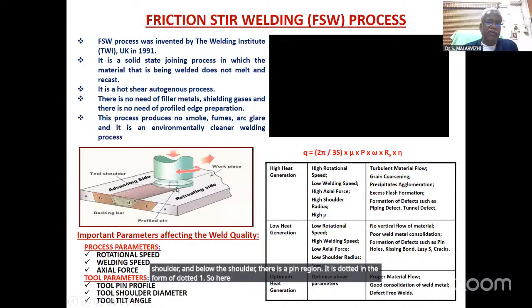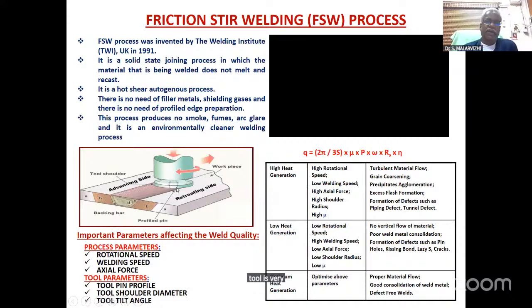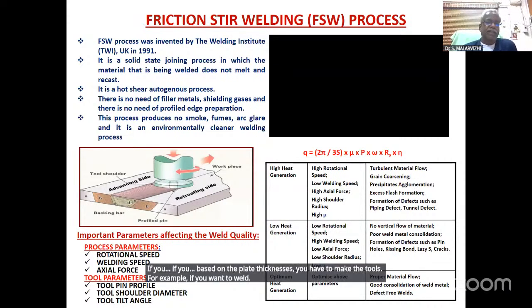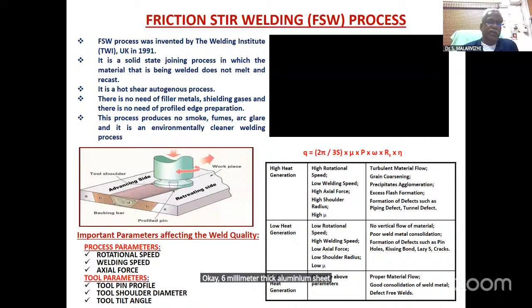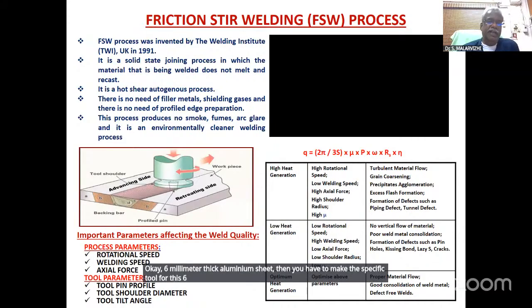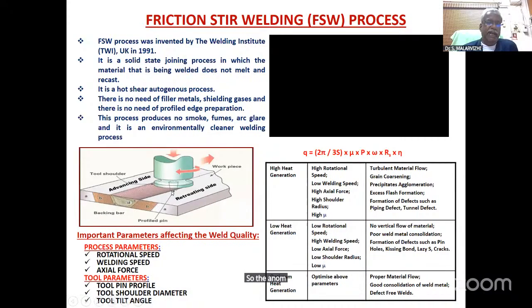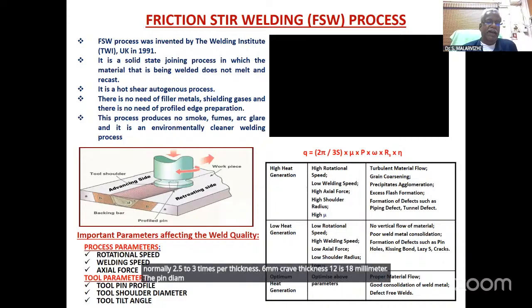Here the design of the tool is very important. You cannot use one tool for all plate thicknesses. Based on the plate thickness, you have to make the tools. For example, if you want to weld a 6 millimeter thick aluminum sheet, then you have to make a specific tool for it. Normally the pin diameter is equal to the plate thickness, and the shoulder diameter is normally 2.5 to 3 times the plate thickness. For 6 millimeter plate thickness, the shoulder diameter is 18 millimeter, the pin diameter is 6 millimeter, and the pin length is 1 mm or 0.5 mm shorter than the plate thickness. So you have to make a tool and use it.